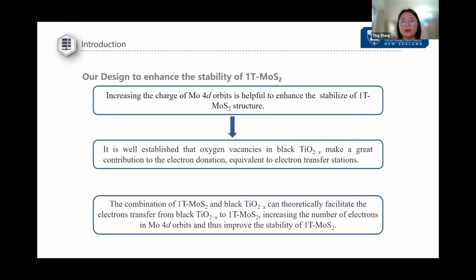Because we want to enhance the electrons in Mo 4d orbit, we do need an electron donor. Our group has researched black titanium dioxide for a couple of years, and according to our research, we found that oxygen vacancy in the black titanium dioxide can make a good contribution to electron donation, and it can be recognized as the electron transfer station.